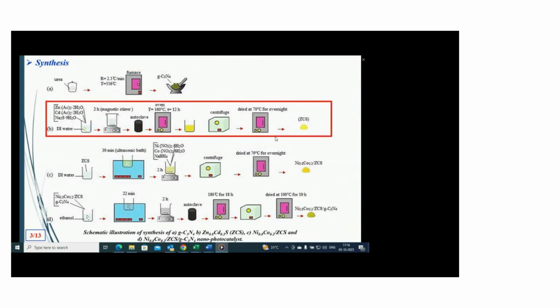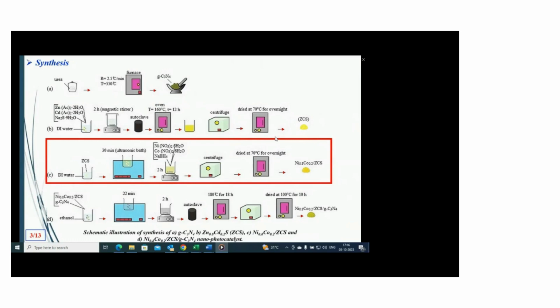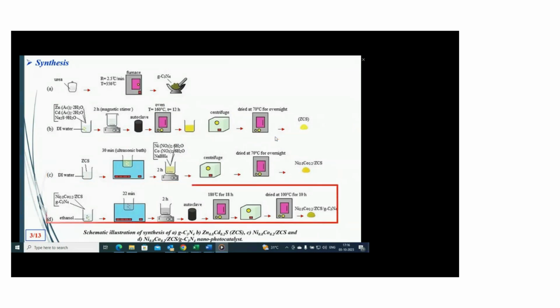According to figure B, ZnCdS was synthesized through a hydrothermal method from zinc acetate, cadmium acetate, and sodium sulfide as precursors. According to figure C, NiCo-ZnCdS was synthesized from previously synthesized ZnCdS and nickel nitrate, cobalt nitrate, and NaBH4 as precursors. And finally, the ternary nanophotocatalyst was synthesized from previously synthesized g-C3N4 and NiCo-ZnCdS with a simple hydrothermal method, according to figure D.